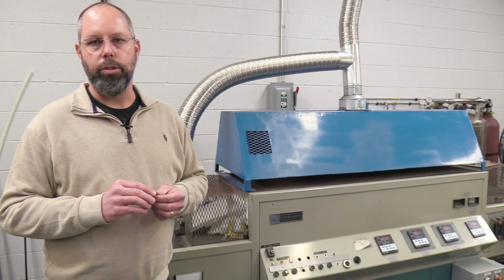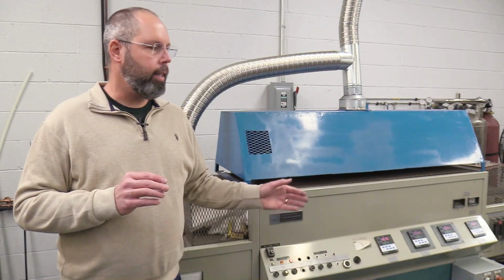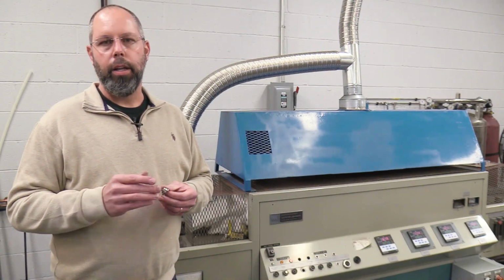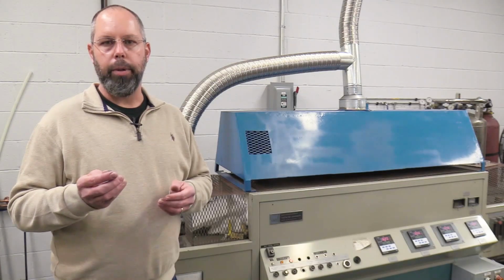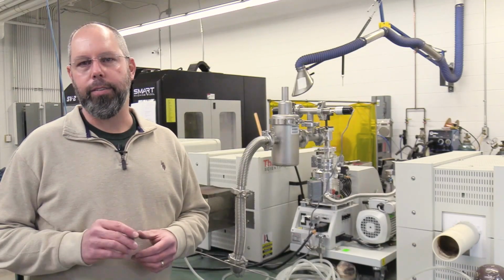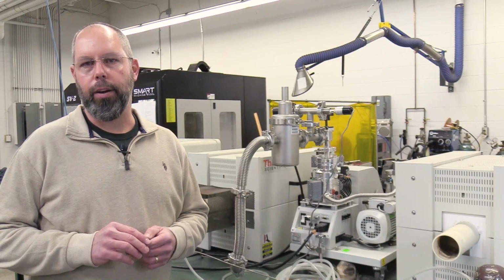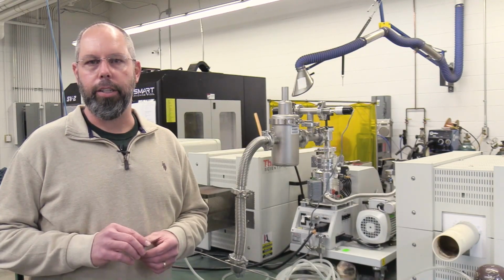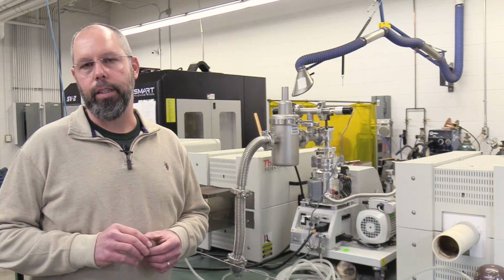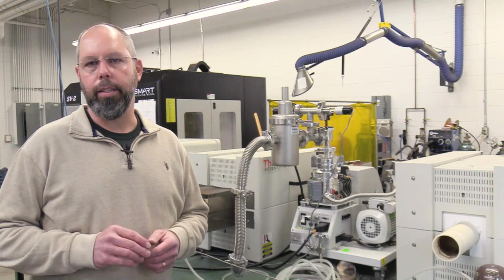giving it structural strength. Then the last zone of the furnace is a cooling zone where you could quench the part or allow it to be normalized. Also in the lab, we have secondary processing furnaces that allow us to do different heat treatments that are seen in the industry. This allows us to tailor the microstructure to meet the desired needs.